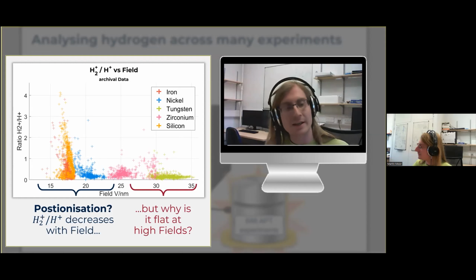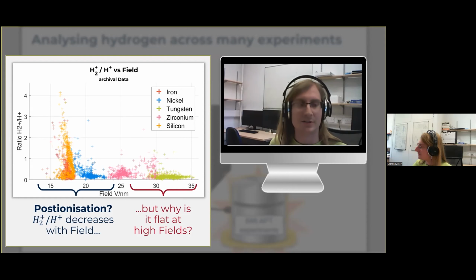But then there is also this high field regime here, which we see above 25 volts per nanometer. And that's coming in a bit surprising because we see that in this region, the hydrogen ratio appears independent of the electric field. In particular, we see that this is not saturating at 0, but at a value slightly above that. And what this is essentially telling us is that the H2+ peak never goes away in laser mode APT. Even at very high electric fields, all of these experiments contain a H2+ peak.